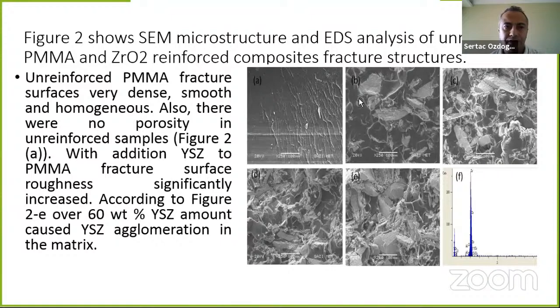Figure 2 shows the SEM microstructure and EDS analysis of unreinforced polymethyl methacrylate and zirconium oxide reinforced composite fracture structures. Unreinforced polymethyl methacrylate fracture surfaces were dense, smooth, and homogeneous in figure A. Also, there was no porosity in unreinforced samples. With addition of yttrium zirconia to polymethyl methacrylate, fracture surface roughness significantly increased. Over 60 wt% yttrium zirconia amount caused yttrium zirconia agglomeration in the matrix. We can see this in figure E.